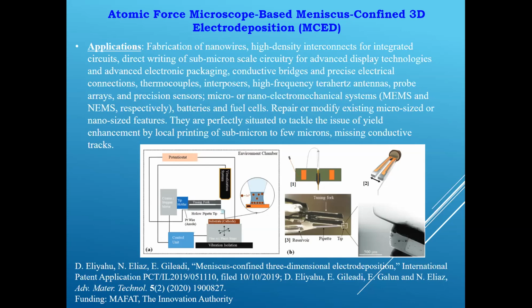For successful printing, the system should have high sensitivity to forces applied on the tip, fast response, and rigid structure. A hollow glass atomic force microscope tip connected to the bottom cantilever of a tuning fork and working in tapping mode with phase feedback was found to meet all operational requirements. Specially designed atomic force microscope tips with pipette orifice diameters of 1 micron, 400 nanometers, and 100 nanometers were used.